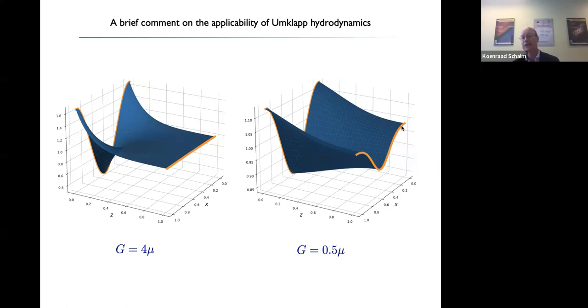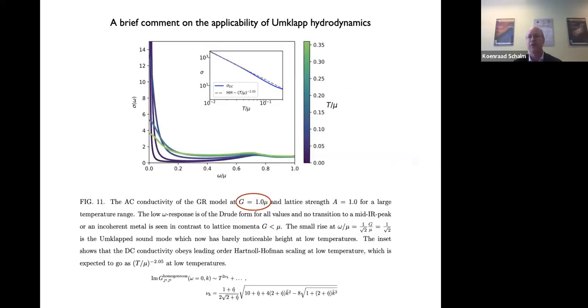So it's important for this effect that the lattice vector is small in units of the chemical potential. And in fact, you can verify this. Here is the same example of, again, the optical conductivity in this system. Now, not even for a super large lattice vector, just G is 1 times mu. And even at the large temperatures, here's this Umklapp sound mode. But nevertheless, for the full regime, it's essentially this Drude-like physics, which is dominated by a Drude-like peak.